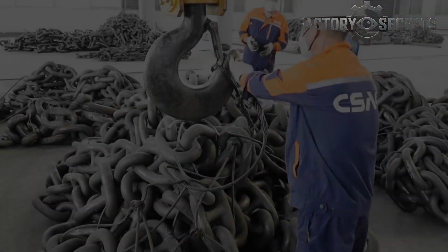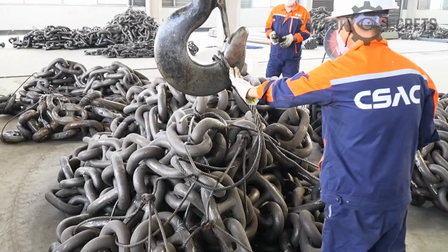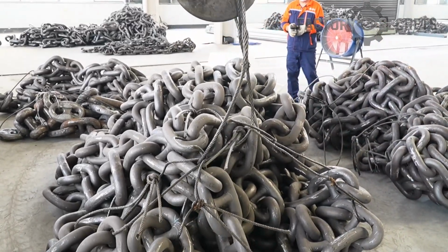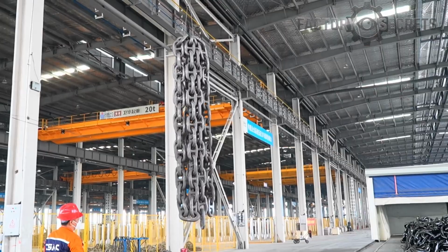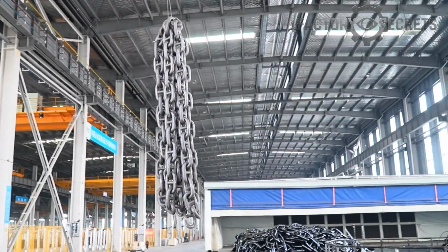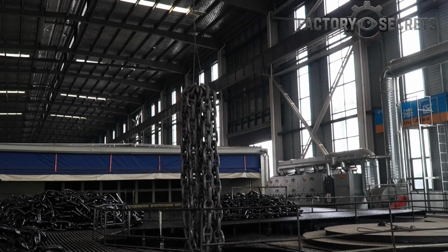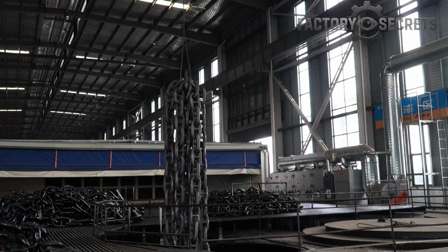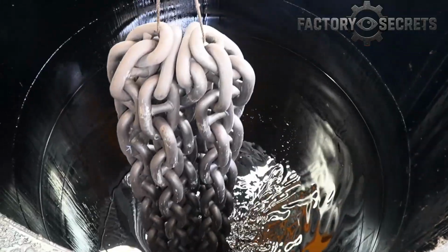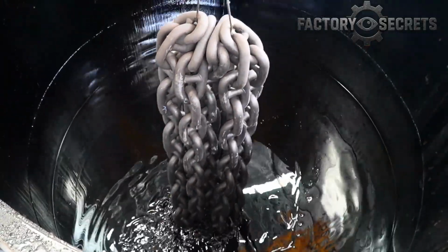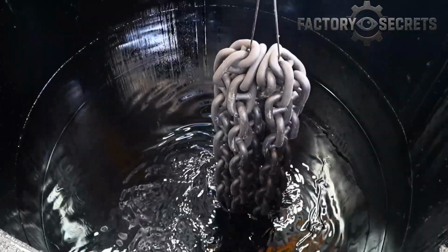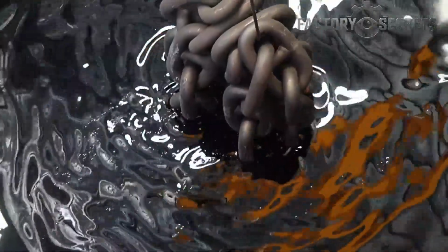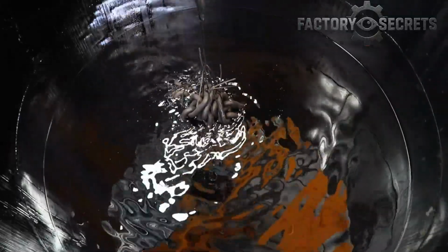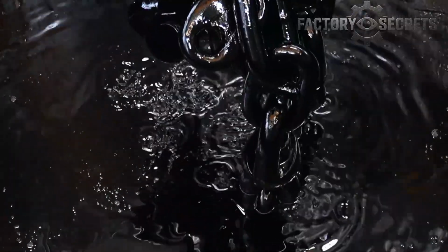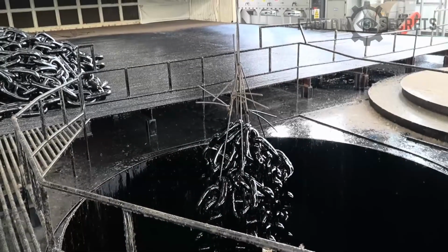One final stage stands between this chain and the open sea. The finished, tested, certified chain is lifted by a crane and slowly submerged into a reservoir of black protective coating, a bituminous or tar-based compound designed to protect the steel from saltwater corrosion, one of the most relentless forces in nature. The chain is held under for a precise duration, allowing the coating to penetrate every crevice, every gap, every surface of the chain. Then it's raised, dripping, glistening, dark, and moved to the drying area.